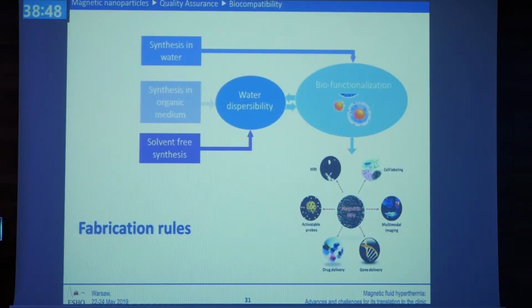So what is the rule then? What is the process we try to meet? We can synthesize nanoparticles in water. That's fine. Water is a solvent which is biocompatible. So immediately we can functionalize them to interact in a specific way with the cells. Then we can have synthesis in an organic medium. When we have synthesis in an organic medium, we have to make sure that the nanoparticles we have created can also be water dispersed, because there are some organic media which are solvents, like hexane or whatever, and we cannot put them inside the body. So we have to make nanoparticles that are always water dispersible, then we can functionalize them, and then we can put them inside the human body.